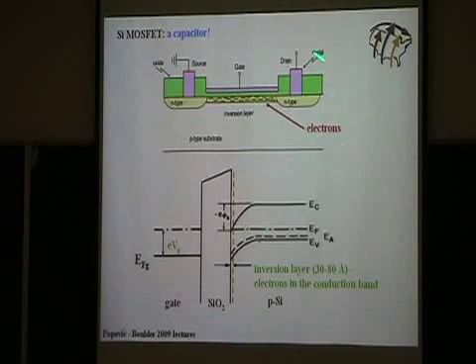And the band diagram for this structure is shown here. So this is for the gate, the metal, silicon dioxide, and semiconductor. Now, because you're putting three materials together, the chemical potentials have to be the same in all of them, which leads to the band bending. So basically, these electrons at the interface live here in this potential well in the conduction band for sufficiently large gate voltage. And the thickness of this layer is typically 30 to 80 angstrom.